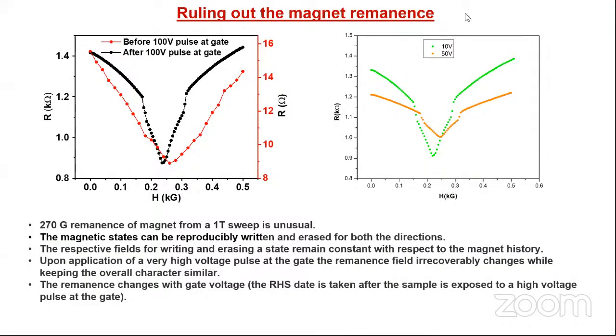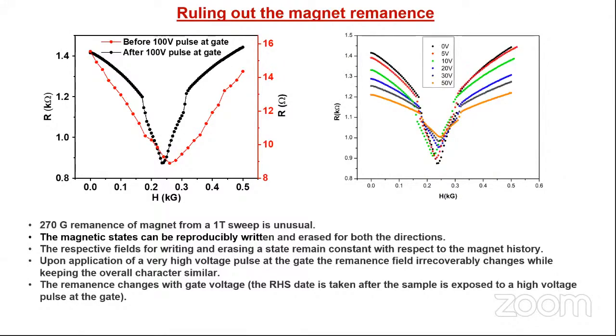So this is again the R versus H graph when the temperature is fixed at the middle of the transition, so that we have substantial resistance to measure. And you can see the evolution of this R versus H with applied electric field, and we see that the remanence that is appearing at the interface is also a function of electric field. So this means the magnetism and the electrical properties in this case are well connected, and these are the experiments that are still going on.